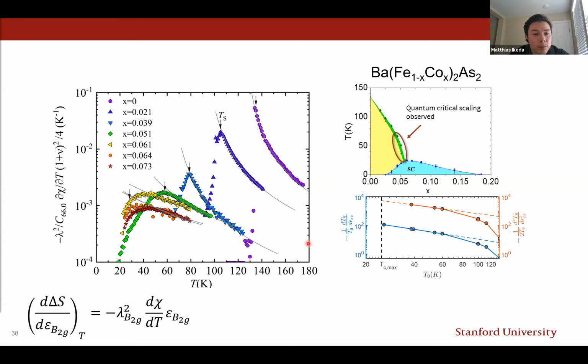I would also like to point out that the perfect Curie-Weiss temperature dependence that we observe for low dopings breaks down for dopings above 4%, or actually 5%. This doping regime in which we observe strong non-Curie-Weiss-like temperature dependence in the nematic susceptibility agrees really well with the regime in which we found strong quantum fluctuations.